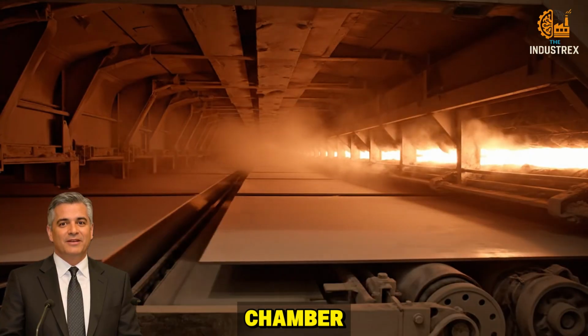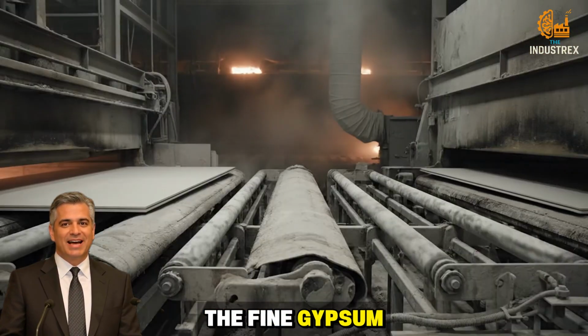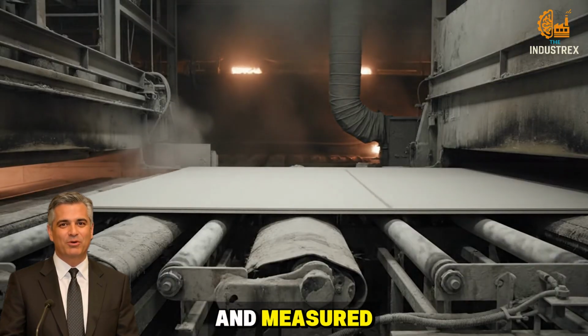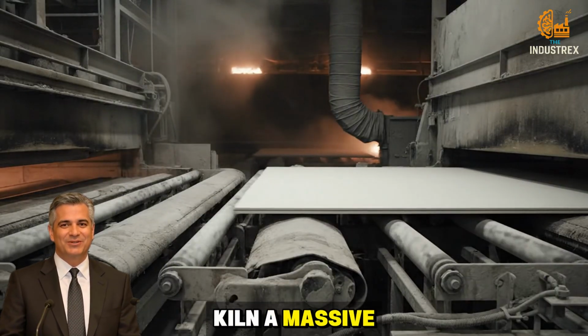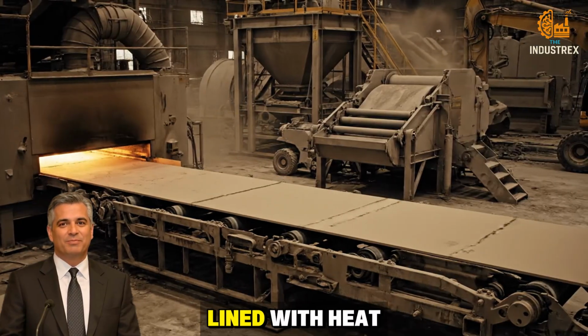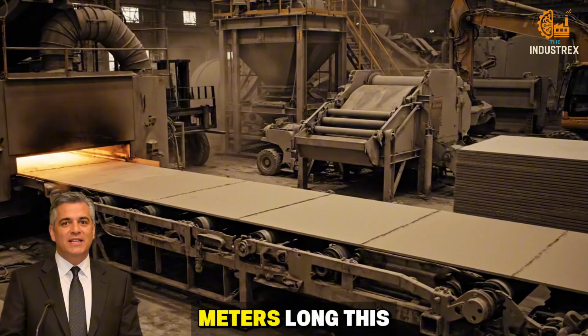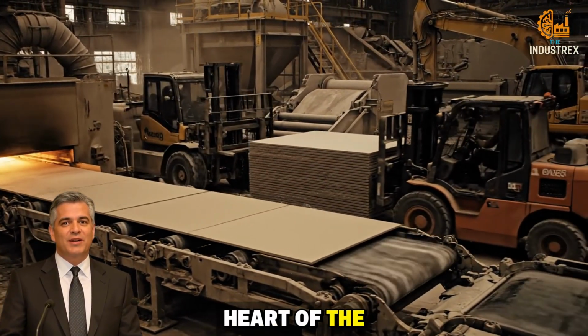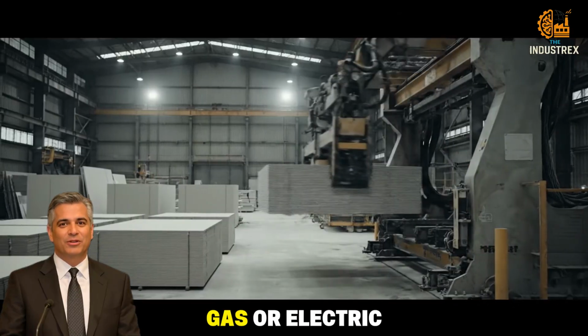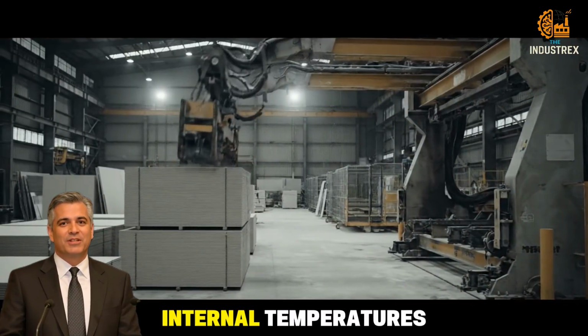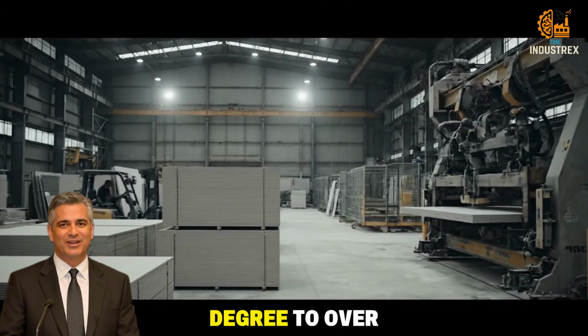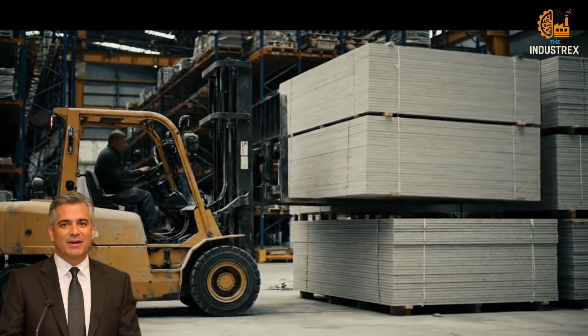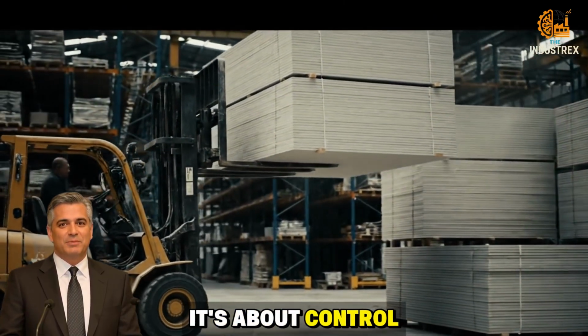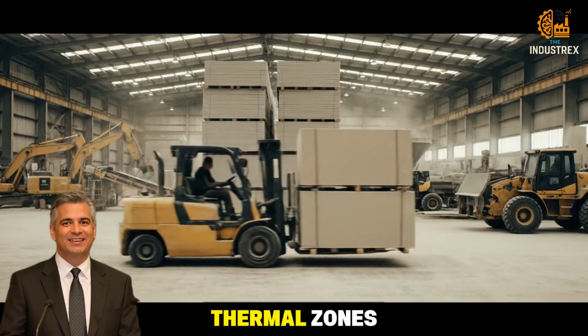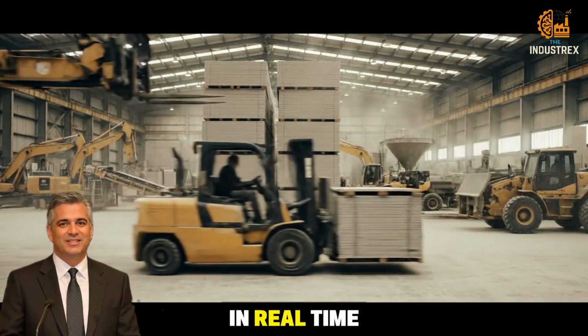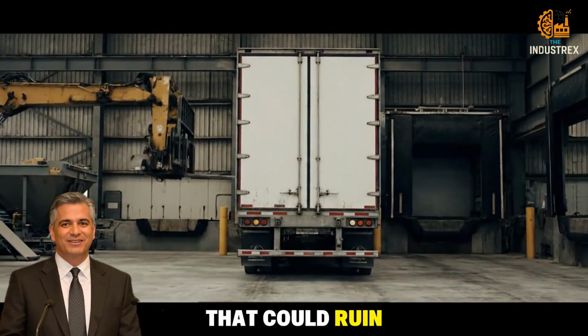Inside the calcination chamber, things heat up, literally. The fine gypsum powder, now carefully filtered and measured, enters a rotary kiln, a massive, slowly rotating cylinder lined with heat-resistant brick. At over 30 meters long, this kiln is the beating heart of the entire drywall process. Fired by natural gas or electric burners, the kiln creates internal temperatures ranging from 140 degrees to over 180 degrees. But it's not just about heat, it's about control. Sensors positioned along the kiln monitor thermal zones, adjusting fuel flow in real time to avoid sudden temperature spikes that could ruin the crystal structure.